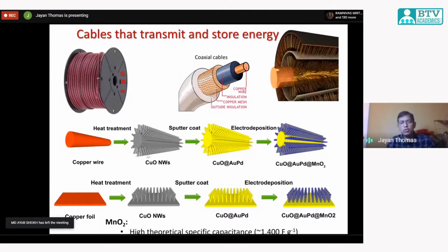So one of the first directions or steps is done by my group, at least in the supercapacitor direction. That is where we try to make some fibers which can store energy. So this is the first attempt we made in that direction. People have been working a lot on the planar supercapacitor device. Even my lab was using it, but we thought about whether we can convert some of the copper wires into a storage device too.